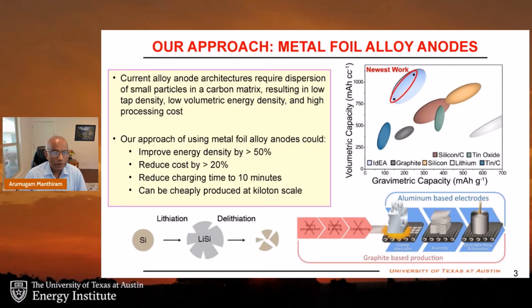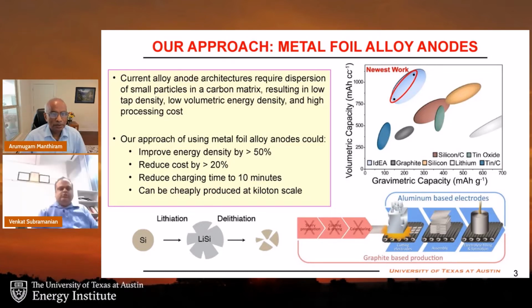So our approach is, instead of graphite, to use alloy anodes, but there is a lot of research that has been done with alloy anodes. Generally, for example, silicon or tin dispersed in a carbon matrix, and that leads to a couple of problems. First, it occupies more volume, so that leads to low tap density. Tap density is a term used in the battery community. That means when you pack, you are not packing it well. It is occupying more volume. If it is occupying more volume, then it will lead to low volumetric energy density.